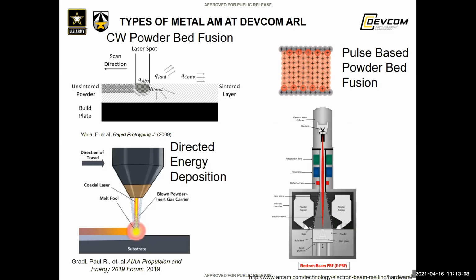And then we have an E-beam, which uses a lot of sintering techniques, because you kind of have to make an electron beam, and then you have the sintering of the powder itself. So we're able to use this for materials that are more sensitive to thermal changes, such as tungsten.